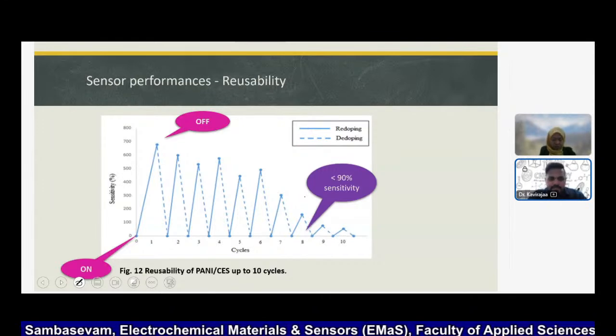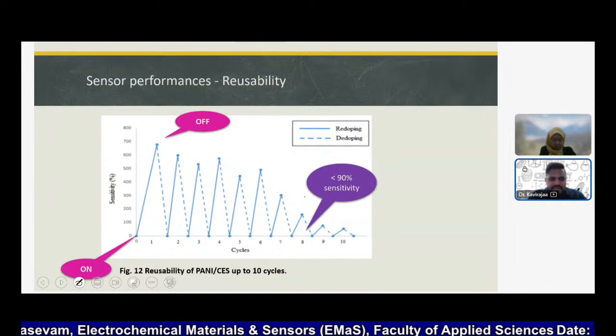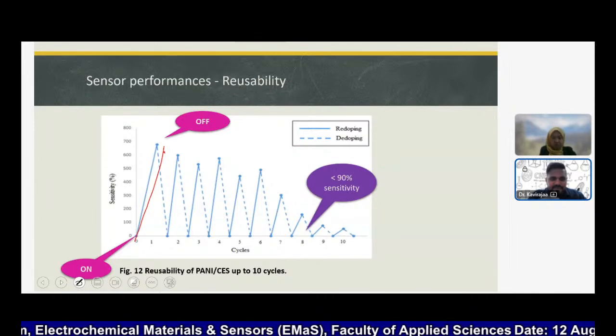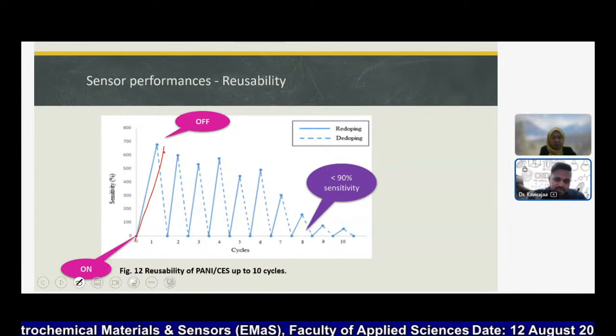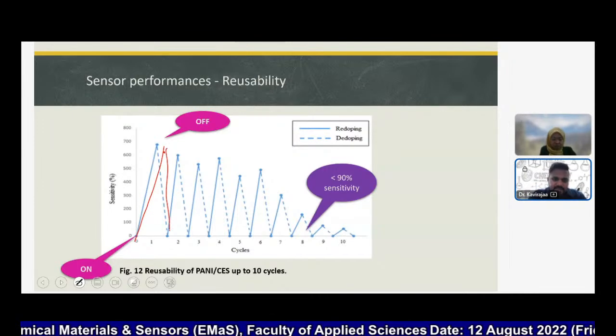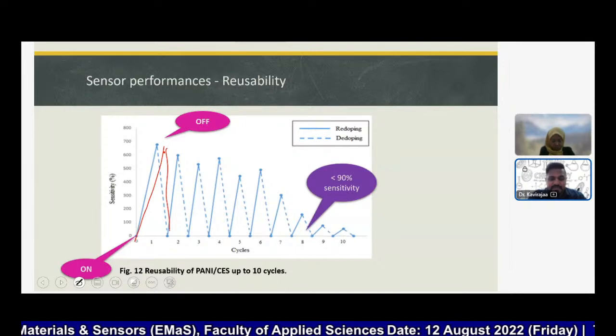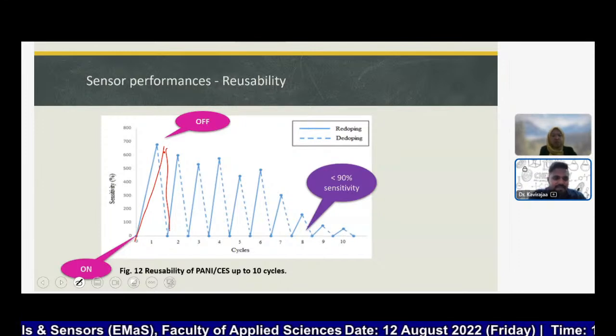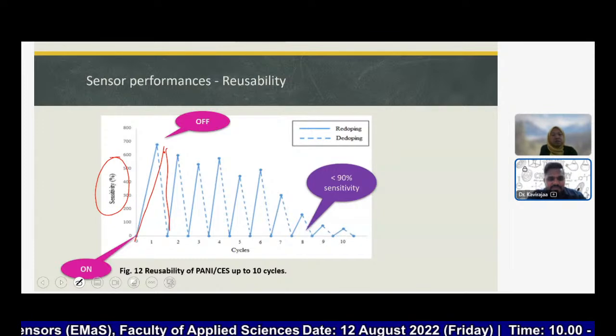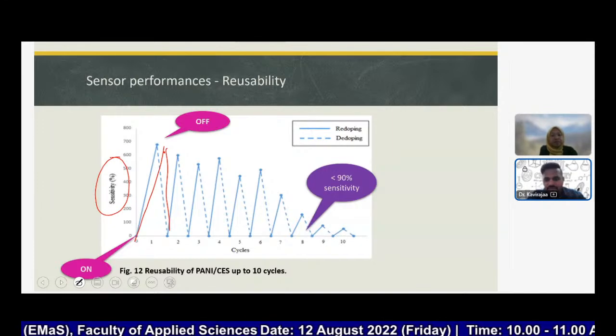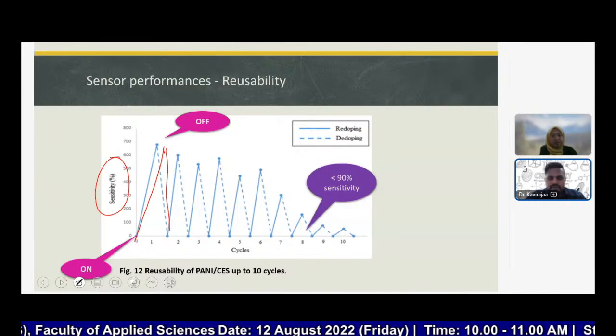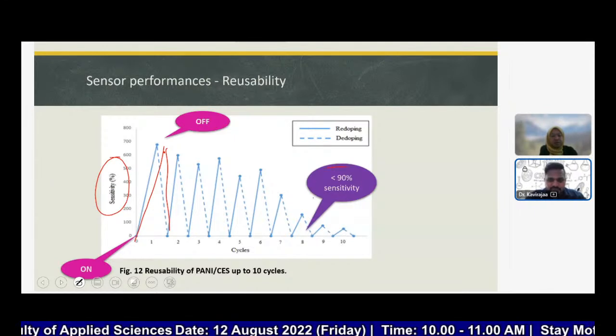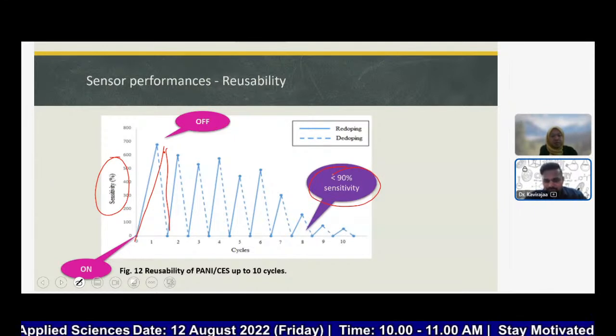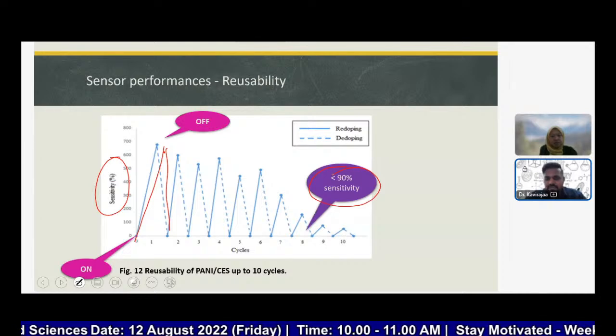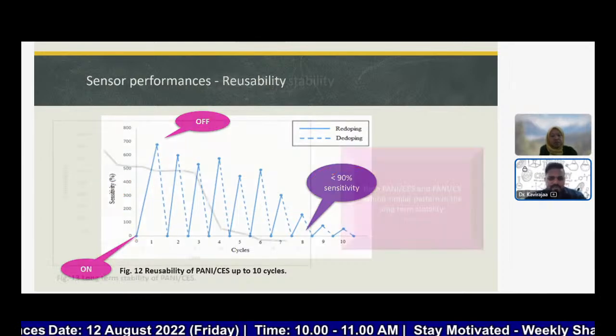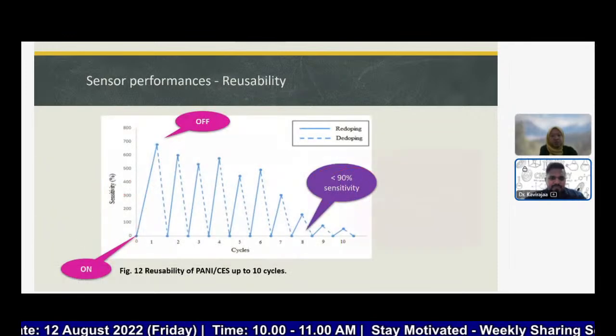So here, when we turn on the gas, that means the target gas, the sensitivity increases, and then when we turn it off, that means when we dedope, it will come back. Right? This is not conductivity. Yeah, this is actually related to the conductivity, but here we respond in terms of the sensitivity. Okay, sensitivity, they got a relative formula. So in this case, we assume if, let's say, the sensitivity drops below 90%, then it's not usable anymore. Right. So next, about long-term stability.